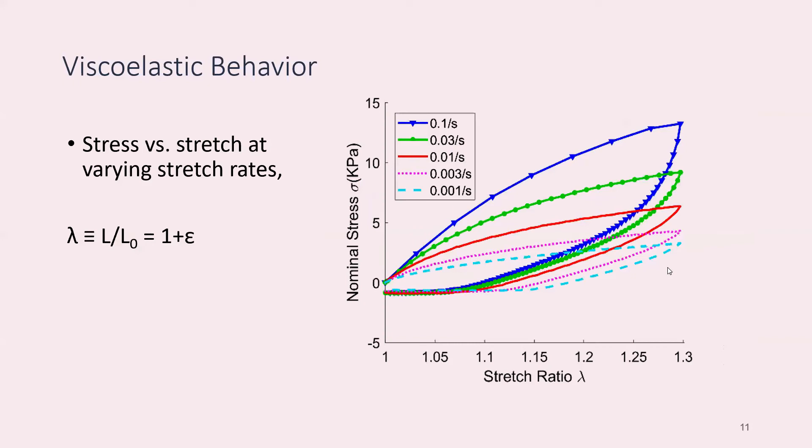Let's start with the experiment. There's a strip of material clamped top and bottom, loaded in tension with a very low-capacity load cell. To keep the gel from drying, the experiments are performed immersed in mineral oil. The loading system is basically just a stepper motor driving a translation stage. The loads are sub-Newton loads, very low. The buoyancy of the mineral oil has to be taken into account in the calibration of the load.